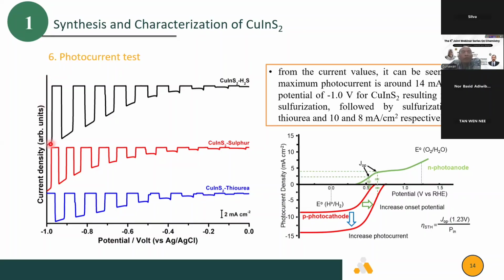Our previous copper indium sulfide also reached up to 14 milliamp per square centimeter. For photoelectrochemical water splitting, the P-type and N-type should meet each other, so that we don't need a bias, I mean, without electricity from outside, without applied potential. So by combining the N-type and P-type, photocathode and photoanode, we can produce hydrogen